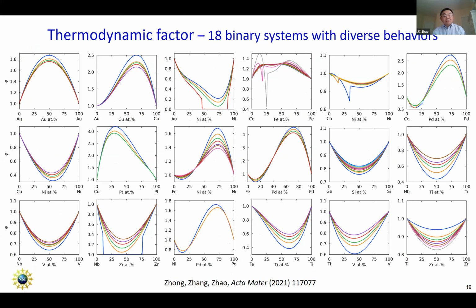And again, if you look at the thermodynamic factor, the other important thing to point out is that the thermodynamic factor is temperature dependent, right? In the binary system, the Arrhenius equation gives the temperature dependence for all the impurity and self-diffusion coefficients, and the thermodynamic factor has a temperature dependency. The entire binary system's temperature dependency is already fully described by those dependencies. There's no need to add another parameter into it. That's what we found.